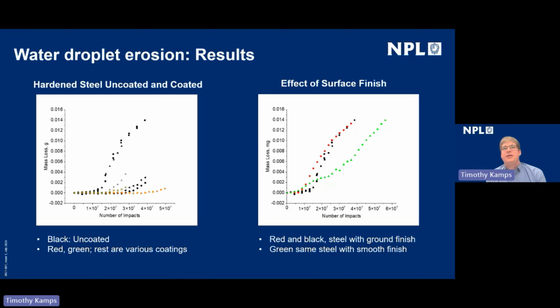It's important to also look at the effect of surface finish as well as the effect of coatings. And on the right-hand side of the slide, we can see results for a smooth and a ground hardened steel surface. So the green line is the smooth finish, and the red and the black are with the ground finish. And what we can see is that although the incubation period doesn't actually change very much in length, when we reach that period of maximum erosion, it does actually take a while for the smooth finish to achieve the same